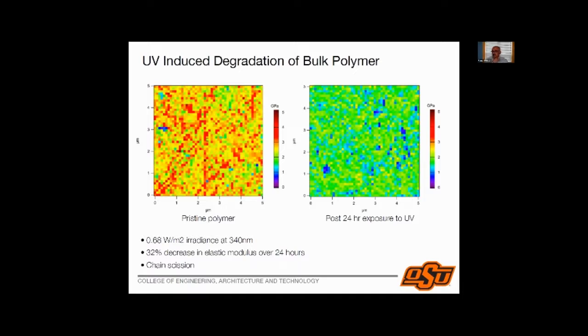The second question we ask now is, now that we have this interface, how will this interface be affected by an environment such as UV degradation? So UV degradation of polymers has been well studied. If I take a pristine polymer and expose it to UV radiation, this is what I get. Again, this is AFM data. They both are exposed to exactly the same conditions, and both these 2D plots are on the same color scale. So you can see that you go from a modulus which is closer to 4 or 5, to a modulus of 3 or 4, to a modulus which is closer to 2. So you see a decrease in the elastic modulus if you take a polymer and expose it to UV.